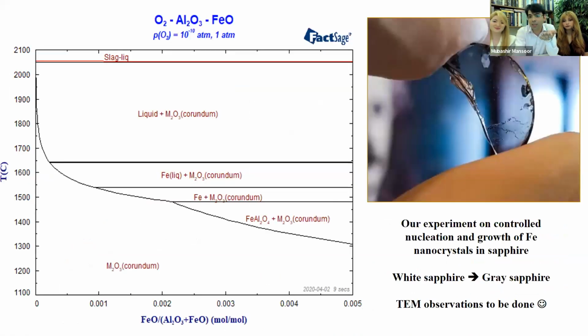Exactly. And we thought, well, let's do it ourselves. And this is the result of our own experiment, in which we actually created gray sapphires. This gray sapphire was very fun. I also shared it on social media, which created a little bit of tension among some of the viewers. But it's actually interesting because you can create these nanocrystals of iron inside your sapphire. It's a synthetic Verneuil sapphire where we intentionally crystallized some iron nanoparticles, and that created those gray shades. And if you see a gray sapphire, which looks very similar to a spinel, it could very well be treated at a very low temperature. So be warned about that.